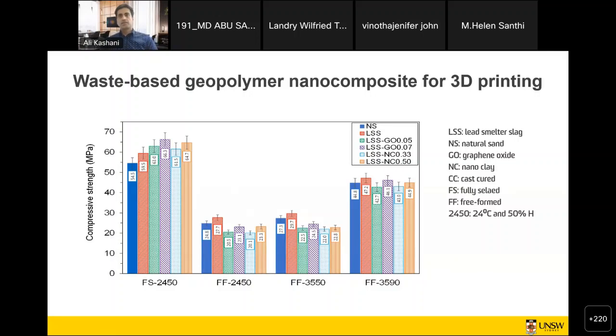Another study that, again, our PhD student Mohsen has been working on, and has recently submitted, is based on a geopolymer nanocomposite for 3D printing. We used lead smelter slag to partially replace natural sand, and also we used two nanomaterials, which are nanoclay and graphene oxide.